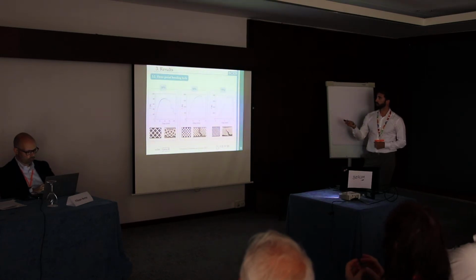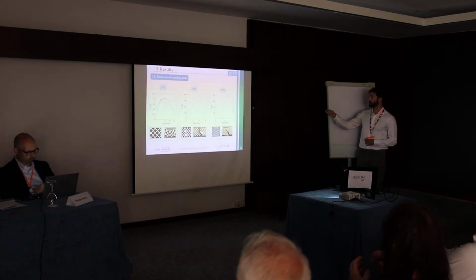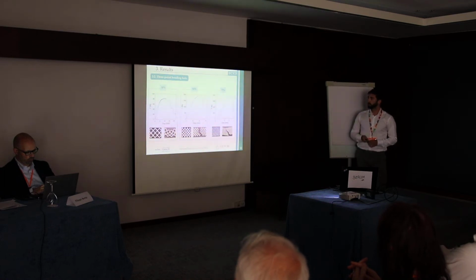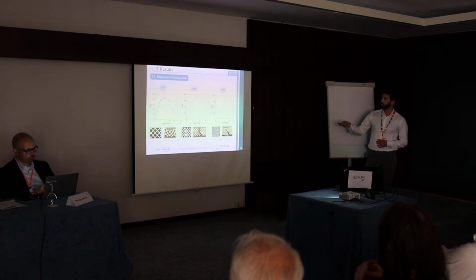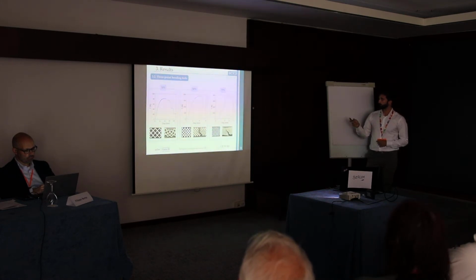Yeah, now with the three-point bending test for the 30, 50, and 75% specimens. Here are the force displacement curves again, and below the specimens before and after bending. In the case of the 30% specimen, we can see again large displacements. Then for the 50 and 75%, an abrupt fracture in lower displacements. And as expected, the maximum force increases while we increase the percentage of the infill.